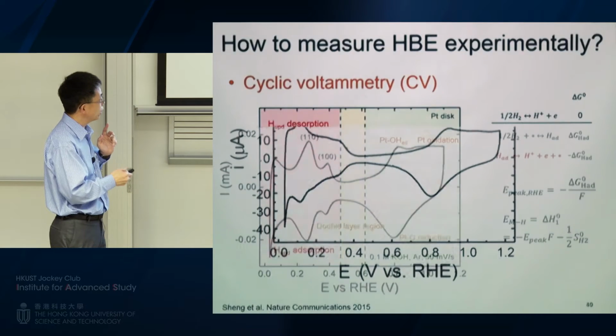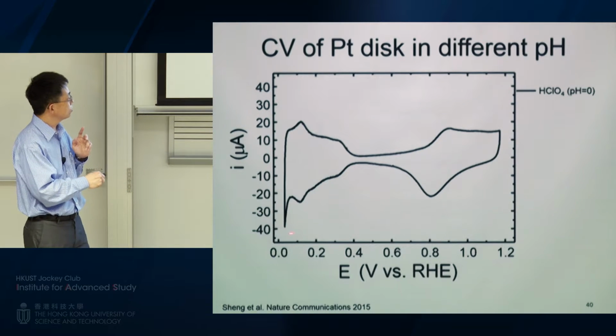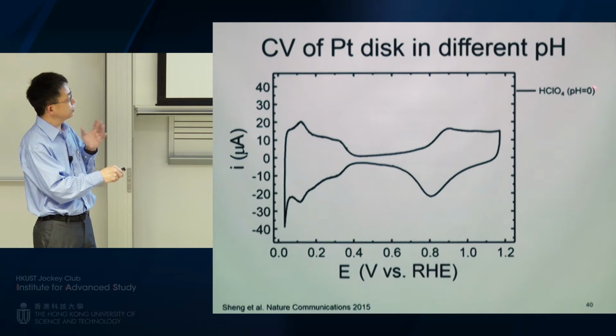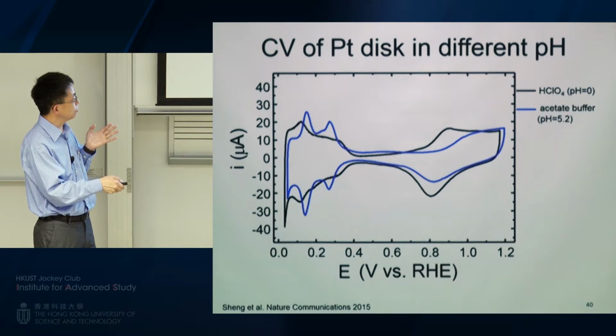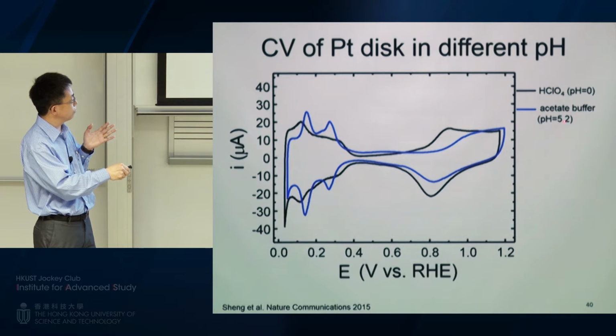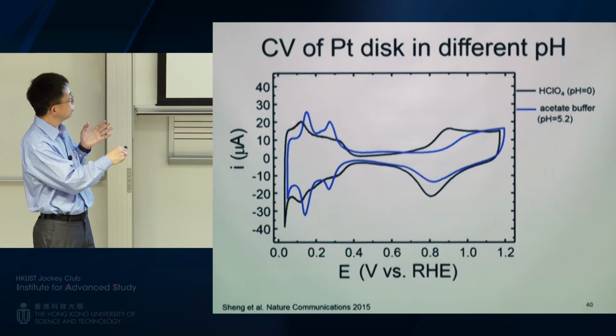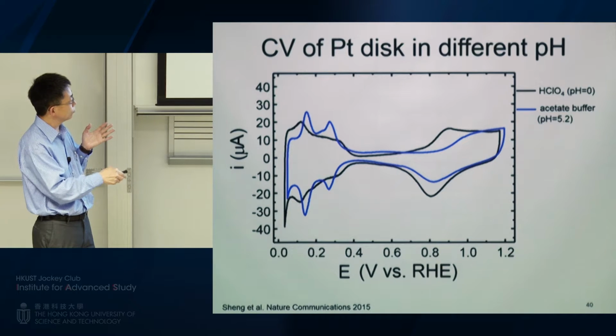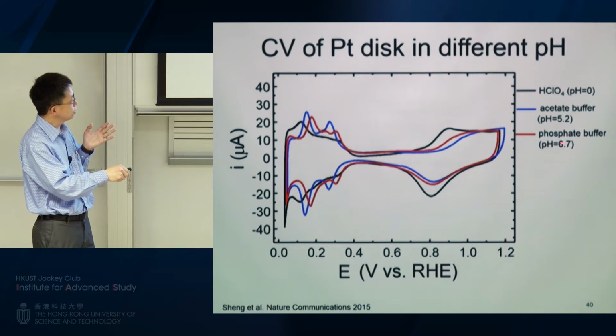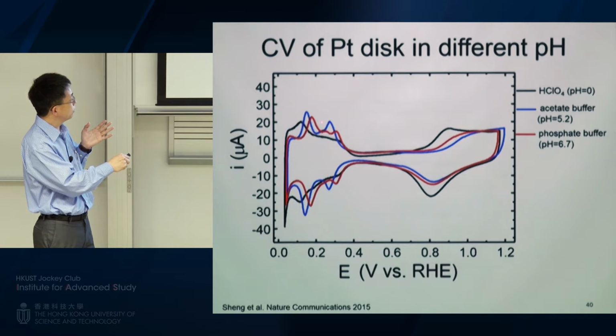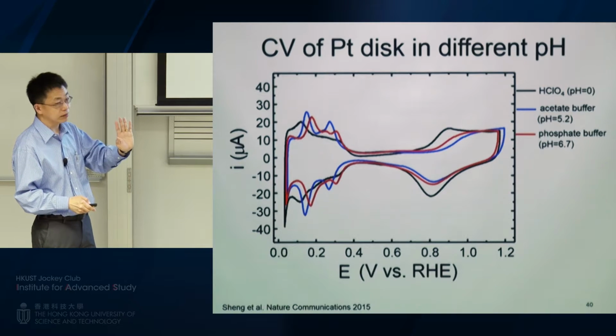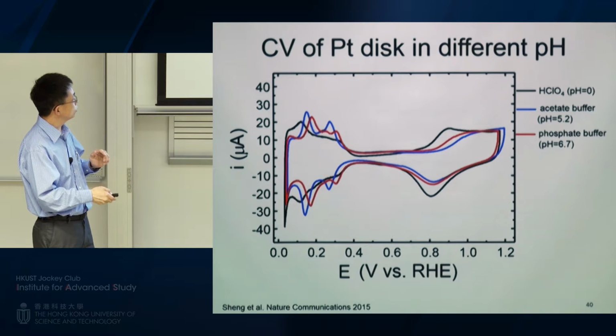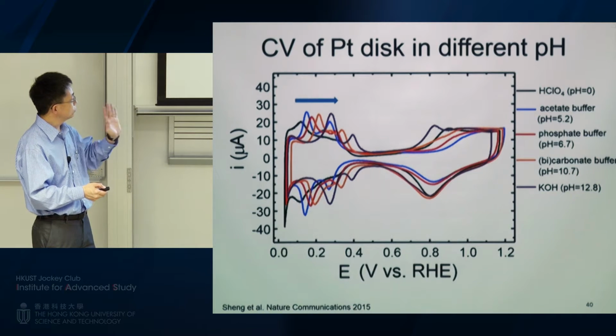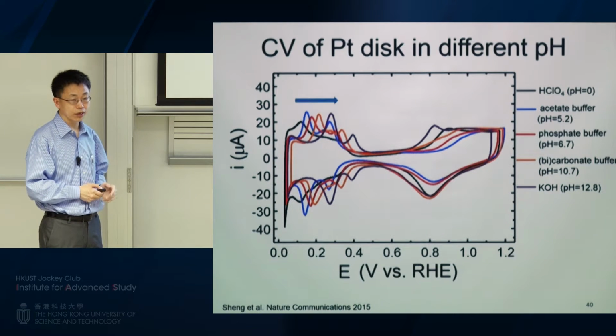So once you know that, we started doing experiment. So we have a CV at pH 0, very acidic. And then we started moving the pH up to an acetate buffer, 5.2. So you can see the peak is moving to a higher potential. And then if you increase this one to 6.7, the peak is moving to an even higher potential. And then you just keep going, and then just going higher and higher.